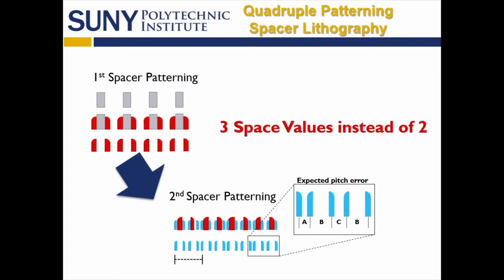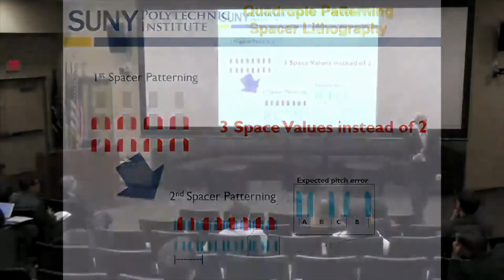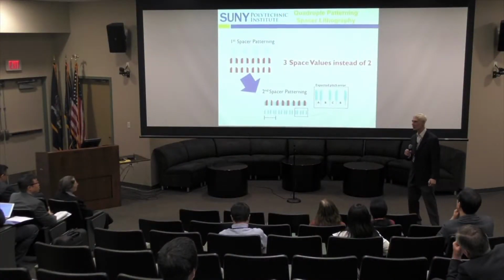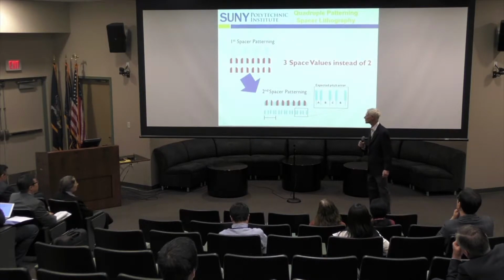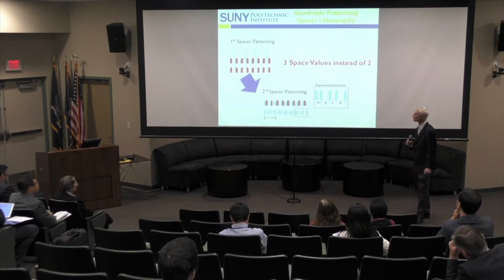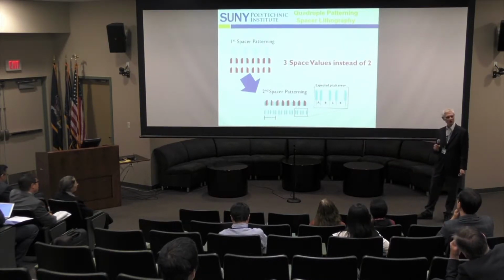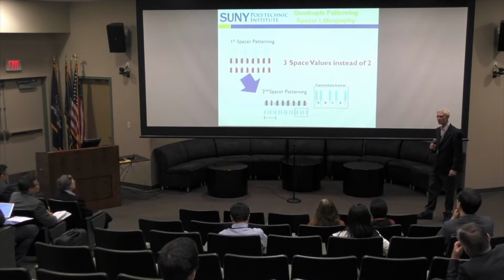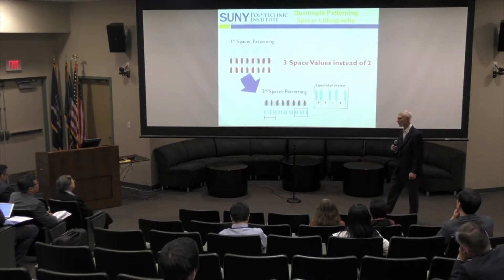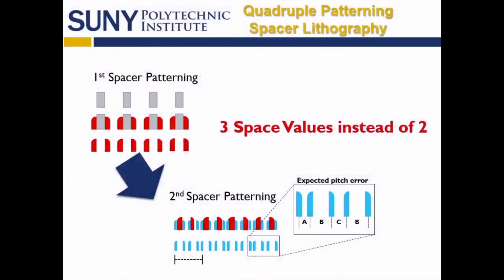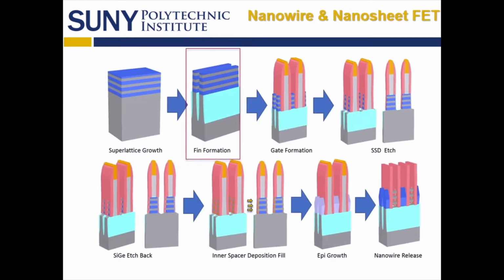All right, it turns out that was hard, but it's way harder now because people are doing quadruple patterning. As it's difficult to put EUV lithography in place, they've decided to do two spacer patterning process steps, or quadruple patterning, and so you get three different spaces in there. So now for all of your measurements, if you're trying to do CD-AFM, this is something to consider. It's very hard to do this kind of measurement, and it turns out you can see this in X-rays, but if you're doing inline process control, this is a real problem.